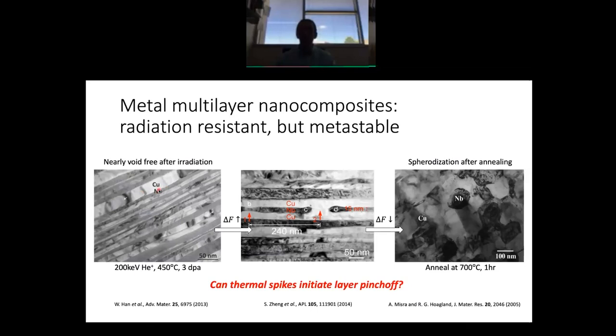In other words, there's a very large number of interfaces per unit volume. Those interfaces are sinks for radiation-induced defects, right? So these multi-layer composites are quite radiation resistant because of that. Indeed, this material that I'm showing you here on the left was actually irradiated to a dose of 3 displacements per atom using helium ions. And if I had been looking at just pure copper or pure niobium, I would have seen a lot of voids forming in the pure copper and the pure niobium.